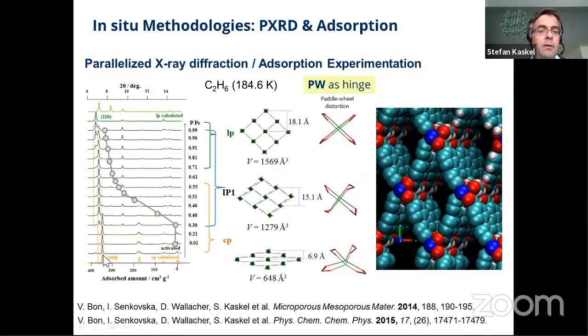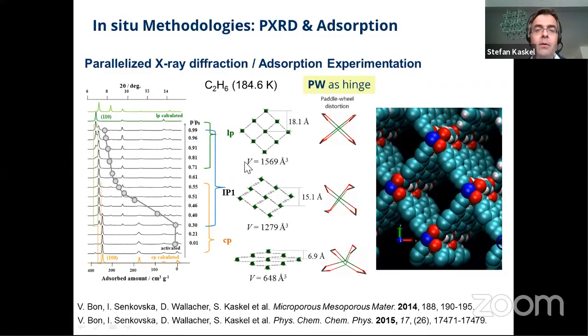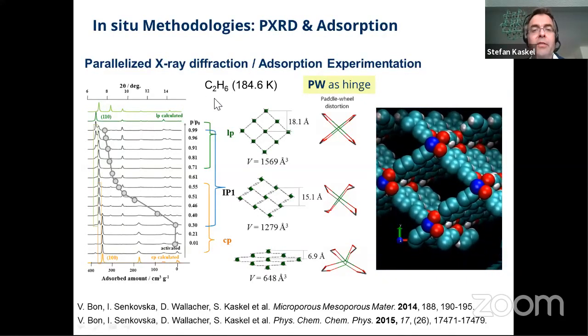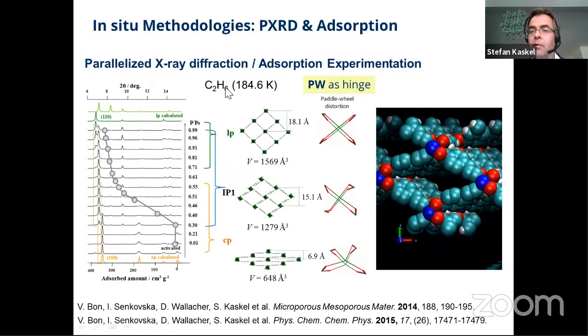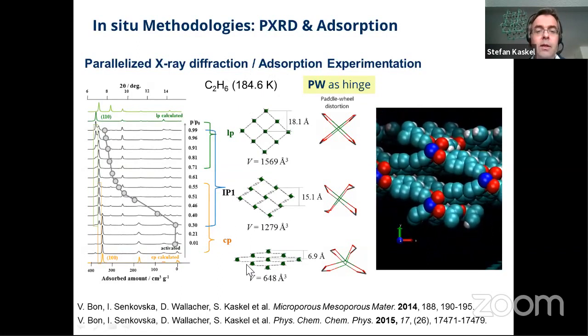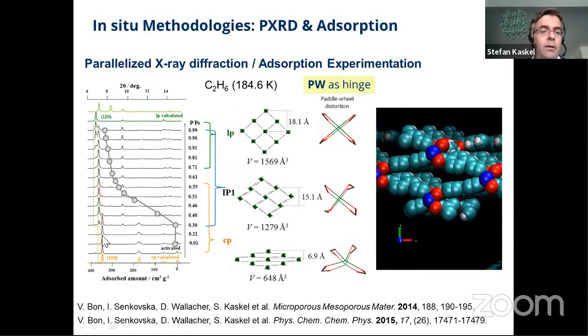So this is one example for in situ diffraction. You see the powder patterns here developing. For just one example, ethane adsorption. This is the boiling point of ethane here. And you see that basically here one powder pattern changes at 0.3. You see a new powder pattern developing, and at 0.8 in P over P0, there's a new powder pattern developing.